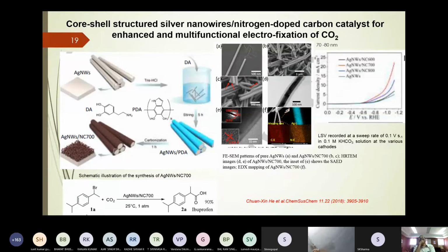Core-shell structured silver nanowires on nitrogen doped carbon catalyst for the conversion of CO2. How can we form this type of nanomaterial? For example, silver nanowire obtained by chemically reducing silver nitrate with hydrazine. So we have dissolved it in HCl with dopamine, followed by stirring with PDA, polydopamine, to form silver nanowire PDA. Carbonization then gives silver nanowire on nitrogen doped carbon, at 700 meaning the temperature, so about 700 degrees centigrade.